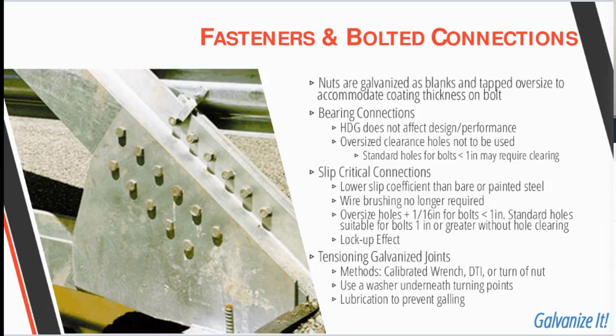There are just a couple more design considerations when specifying hot dip galvanizing for bridges. These include details for structural joints in bridge designs, and these can help save some time and money during installation. For bearing type connections, hot dip galvanized coatings do not impact the overall design, performance, or design strength considerations. As far as clearance hole sizing, standard holes should be specified, but for bolts that are nominal size 1 inch or less, you may need to clear the holes after galvanizing to ensure the bolts can fit the hole.